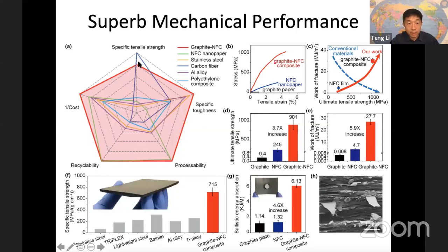The one thing which is not as good as is the carbon fiber. We know carbon fiber is super, super strong. It has a strength of several gigapascal. Well, not that strong, but you know that the carbon fiber has two limitations. First, it's a one-dimensional building block, and we can't make paper, and we can't make two-dimensional film. And second, carbon fiber is very, very expensive, okay?